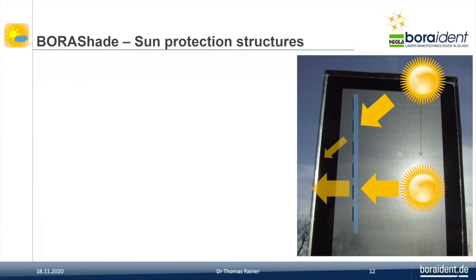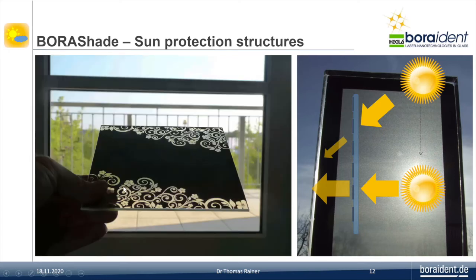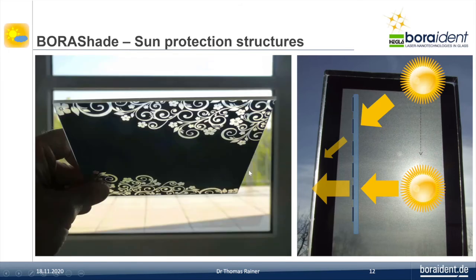The next example is a good one to combine laser technology with traditional glass processing technologies like screen printing. You see here in the photo screen printed glass with black screen printing. In the first stage, the glass was fully printed. And then with the laser, we drilled holes inside this coating. You see here the cross section of this glass. These are the black color, and the holes drilled by laser. This is this area here. And then you have a shadowing effect, and it depends on the position of the sun. I can show you this in this short movie here. You see the effect of the shadowing. It depends on the angle of the illumination. It's a very good example for the combination of laser technologies with traditional glass processing technologies.